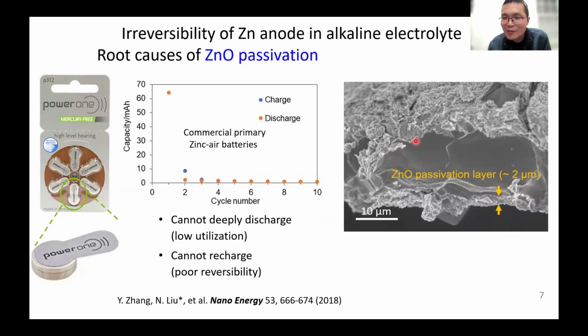As you can see in this image, we fully discharged the zinc, then opened the battery and took a cross-section image. You can see the surface of the zinc is covered by a zinc oxide passivation layer. Inside, you still have a lot of fresh metallic zinc unreacted, but it can't react further because the surface zinc oxide prevents electrolyte from reaching the zinc in the middle and stops further reaction. So that's one of the root causes for the irreversibility of zinc.